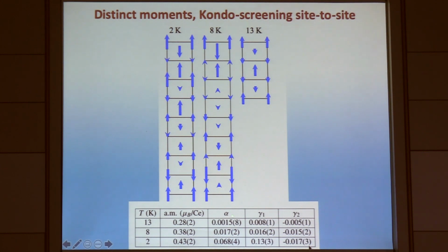There's both a parameter that has to do with the pair term, that tells you how much repulsion or attraction will occur for a given set of spins, but also a term that has to do with how much the environment responds to a spin which is smaller or larger. So the amplitude of the spin actually changes as you go through the structure. So if you look at these pictures here of the spin structures, then you have some spins which are at low temperatures very small, and others which are actually quite large.